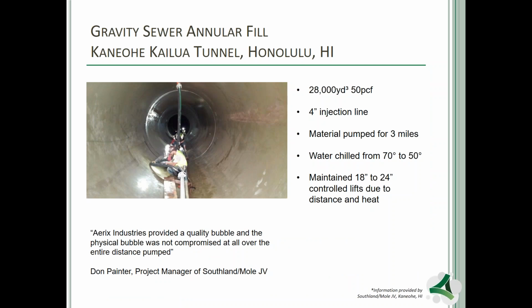And the interesting thing was, from a heat hydration perspective, they actually utilized chilled water because the original water was 70 degrees and they chilled it down to 50 degrees. And in order to control some of that heat hydration over that whole distance, they maintained the lifts at 18 to 24-inch lifts. But again, the bubble quality becomes extremely important to be able to pump over that distance and not have a bubble loss.